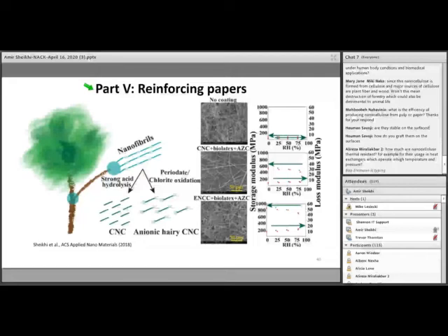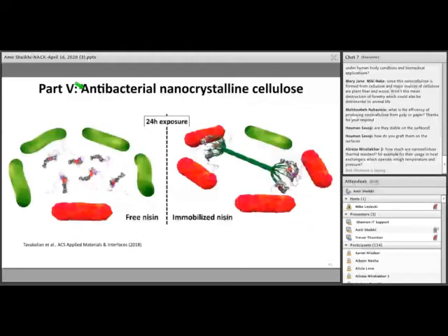We can also use these particles and incorporate them into paper and cross-link them with green binders such as ammonium zirconium carbonate to improve the mechanical properties of papers and replace the environmentally unfriendly latex particles. We can improve the storage modulus, as you can see here, by more than 5 times, using these hairy nanoparticles and get a better quality coating with fewer cracks compared to conventional nanoparticles.